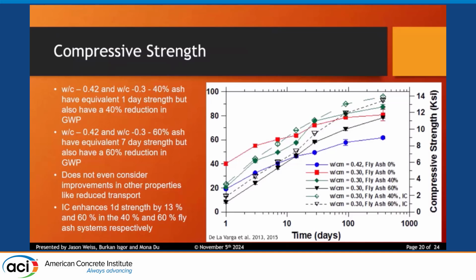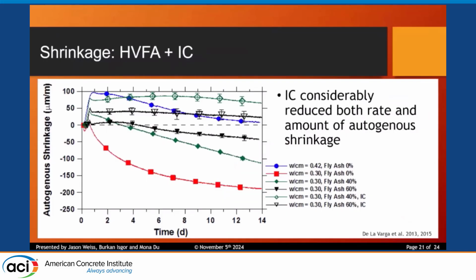And when we first started doing this, people said, well, aren't you going to now start getting lots of early cracking problems or shrinkage problems because you're going to lower water to cement ratios? Well, here you can couple it with internal curing. And the coupling with internal curing has its own benefits because now you're actually curing the system properly, where low clinker systems are going to need attention paid to how we actually cure the systems. So here is our conventional system. Here's the system if we just drop the water to cement ratio. If we add the internal curing, we're back up here where we were with our initial system.